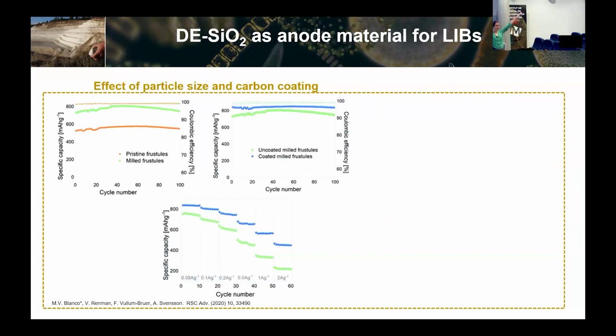Once the capacity was reached after these 5 activation cycles, we can see that with the pristine material, without any ball milling, just the purchased material in the cell, the capacity was 500 something. If we do the ball milling, we increase the surface area and the capacity is much higher. And if we do the coating, the capacity is much more stable, and the rate capability also improves. This looked okay after 100 cycles.